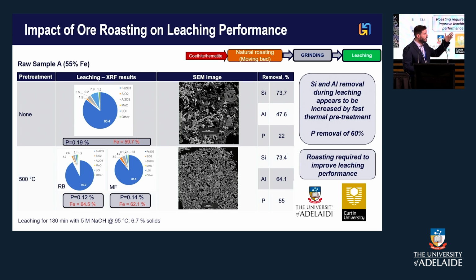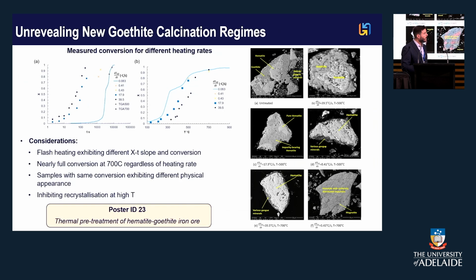So if we do nothing, so no treatment, the ore really responds poorly to the leaching. But when we couple the new heating methods approach and compare that to the performance of slow heating rate roasting, there is an additional impact. You see the phosphorus is further reduced, and also we can achieve for this specific one a 64%, 65% iron, compared to 62% iron if it was heat treated through traditional slow heating methods.